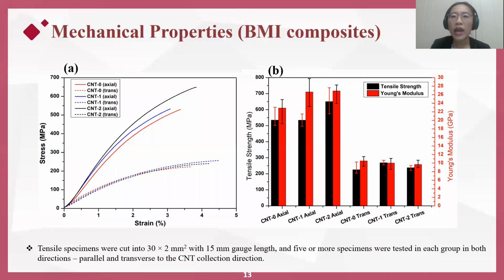By now, I believe that we have gained some understanding about the quality improvement of the as-collected CNT. With resin spraying and the curing process, we fabricated CNT BMI composites with 3 different CNT samples. To evaluate the mechanical properties, tensile tests were performed, and substantial differences between the axial and transverse directions among all the groups can be explained by the stretching-induced alignment during collection.